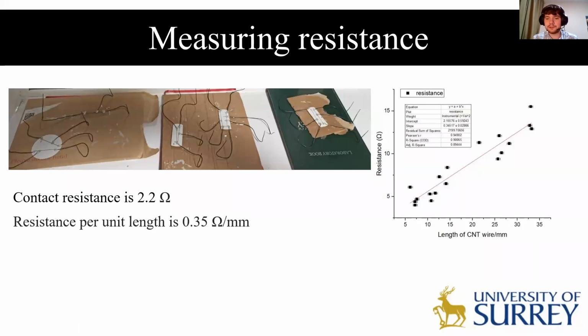The first experiment I've conducted with this set of wires was measuring the resistance at a DC current. This was done using a multimeter, and here are the results obtained. The graph on the right shows how the resistance of a wire varies with the length of the CNT. This is used for working out the average resistance per length of the wire. It can also be used to find the contact resistance, as at length 0, you would only get the average resistance at the contacts of the wire. That was obtained to be around 2.2 ohms.